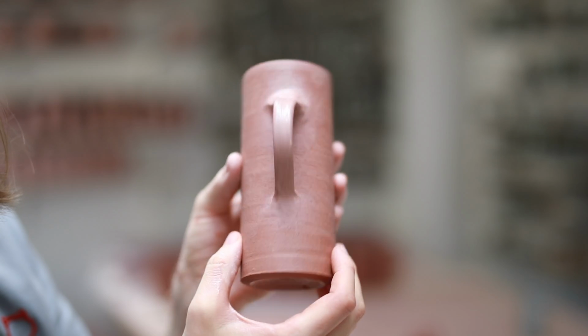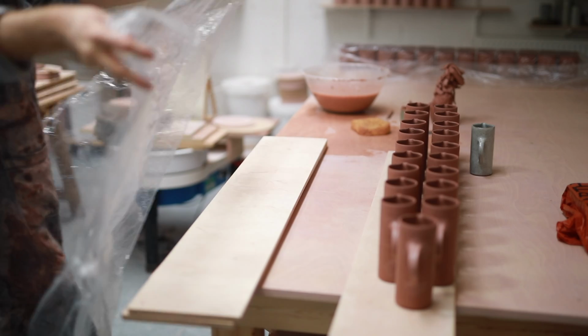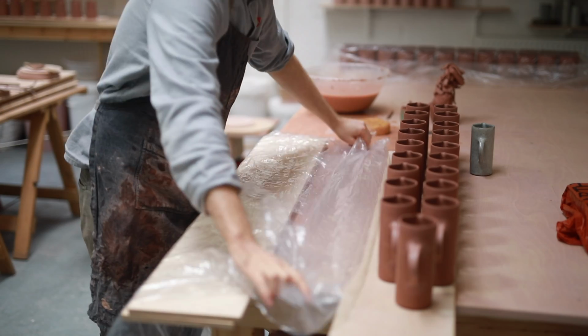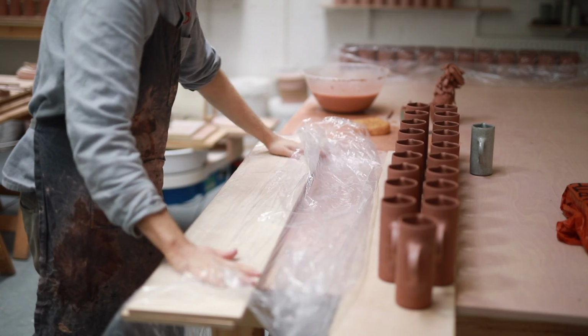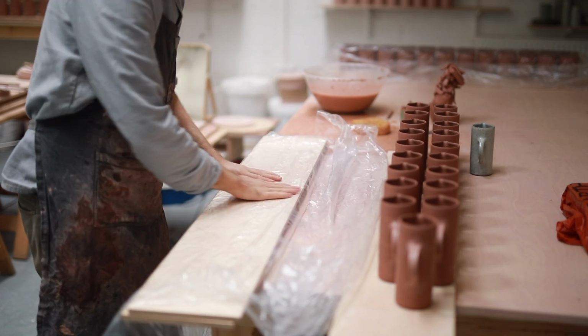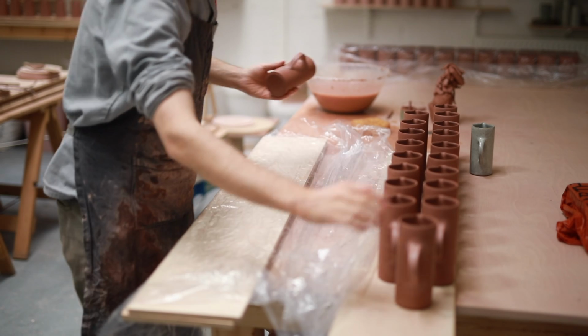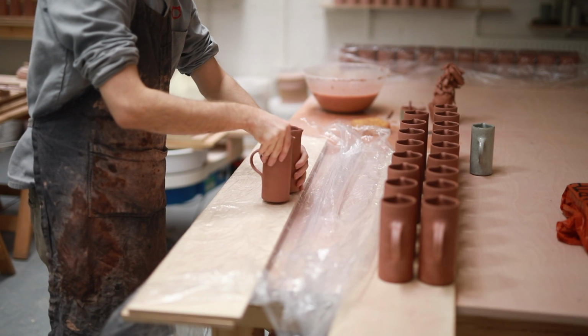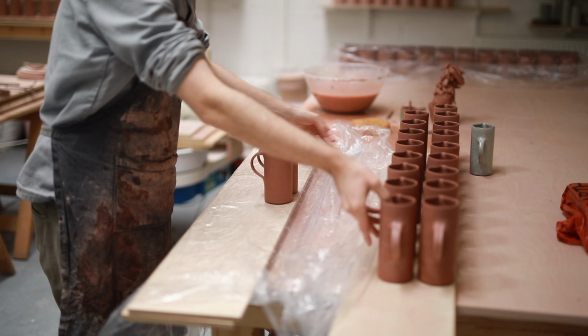As I handled these right at the end of the day, I had to wrap them with plastic overnight, which is good as it lets the clay of the handle, which is much softer, acclimatise to the thrown clay of the jug, which means by morning they'll more or less be exactly the same consistency, which is ideal for when you want to dry them out at the same rate.